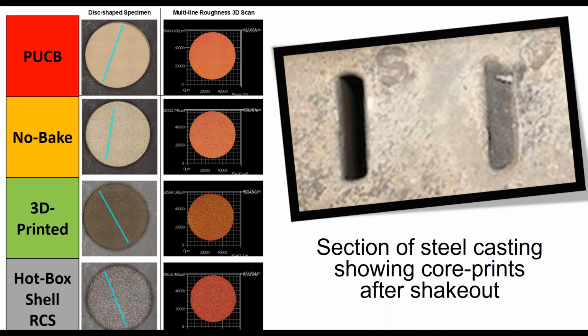Again, the AFS work that is documented and available through them is devoid of a proper understanding on steel castings. We have started that work where we are understanding the mold metal interface at steel head pressures and temperatures relative to surface conditions like shakeout, and then the surface roughness to come up with an overall measure for casting quality. On this slide, I'm showing you a system that could shake out well at a core print for the same energy, and another system that can't shake out on a steel casting, even with a ceramic sand.